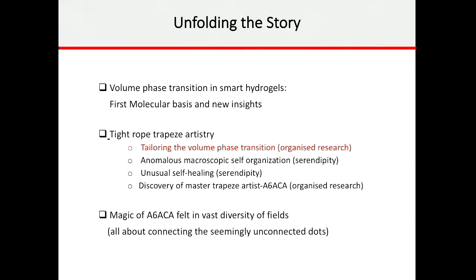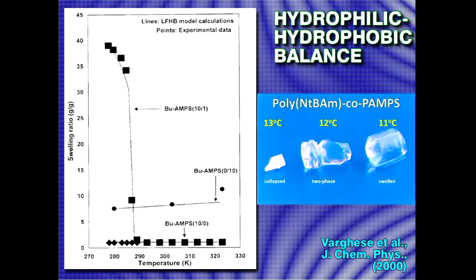Let me then get to the tailoring of the volume phase transition, organized research as I call it. So we started playing around with it, as you saw this transition. So we had this poly-N-tert-butyl acrylamide, which is a hydrophobic monomer, and you have it copolymerized with poly-acrylamido-methyl propane sulfonic acid, which is hydrophilic. So hydrophobic and hydrophilic. And see this very carefully. What you see here is that if you have a total hydrophilic monomer polymerized, you have no transition. You have a total hydrophobic monomer polymerized, you have no transition. But when you make the combination of the two, you see the sudden transition. That is the balance, the hydrophilic and hydrophobic balance, which actually gives you the transition.